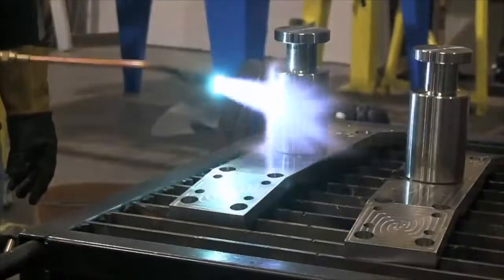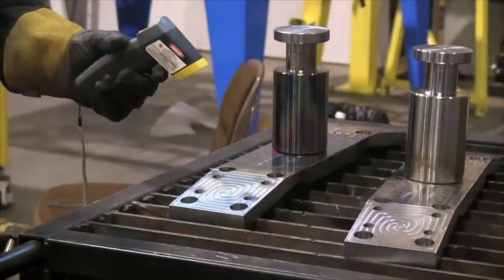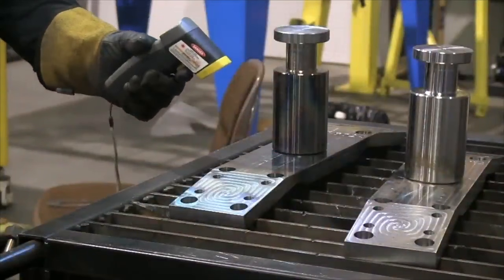It's 4140 material, very hardenable metal. And the procedure called for a preheat of 500 degrees and also to keep it 500 degrees between passes, to not let it get below 500 degrees. And so that's what I did with this infrared heat gun.